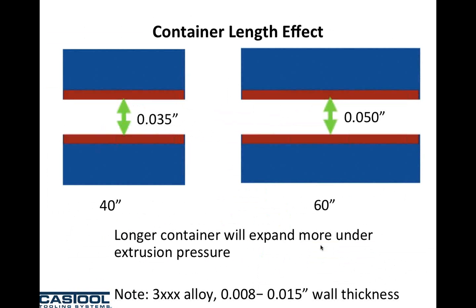The amount of expansion of the liner bore goes up by close to 50%. So the same container, same dimensions, that was 60 inches long, will expand about 35 thou. And depending on the flow stress of the alloy that we're extruding, the aperture between your dummy block and your liner may be big enough to allow aluminum seepage between the two now.